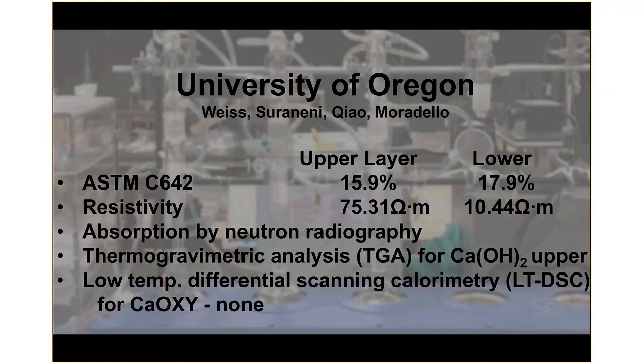So finishing up for questions and answers, the work that was done by Dr. Jason Weiss at the University of Oregon did some C642, which is a basic test for void spaces in concrete. The upper layer came up with 15.9% porosity, the lower 17.9. Resistivity very much higher in the upper layer. Again, this has to do with the non-carbonated, very dense nature of that, so much higher resistivity number versus the lower. He did some absorption work by neutron radiography, which was kind of all over the place.